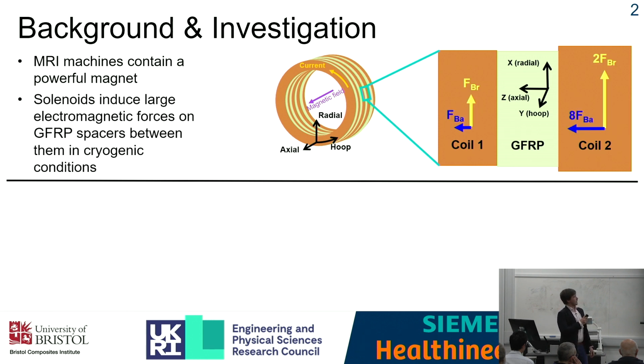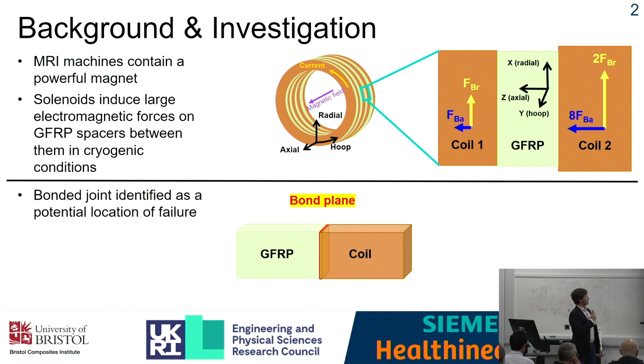These coils apply very large electromagnetic forces when the field is operational, and these forces can exceed 1 meganewtons and are applied on the inner GFRP at cryogenic conditions needed for the superconductive state. Therefore, it's been highlighted that this interface between the GFRP and coil could be the location of failure. And this is the kind of highlight of the work that I'll be presenting.